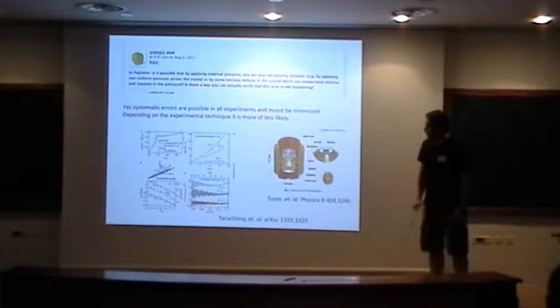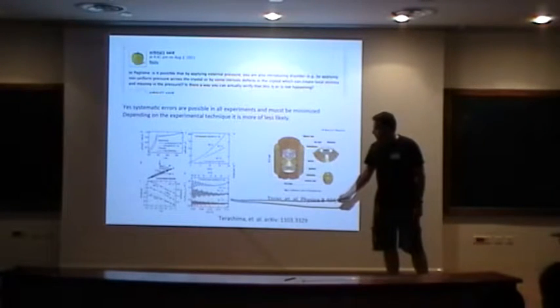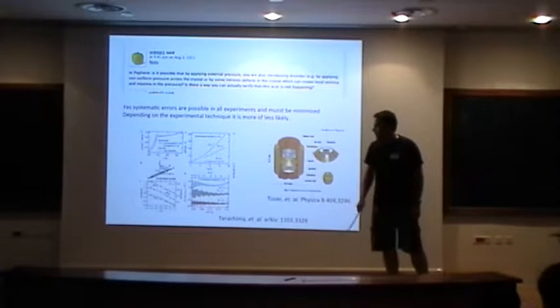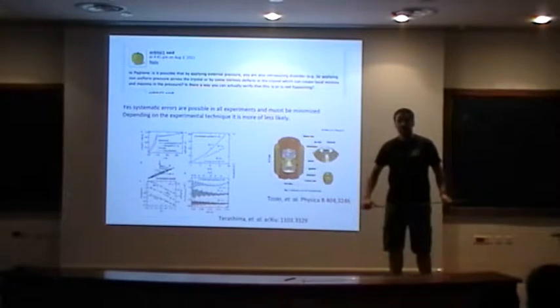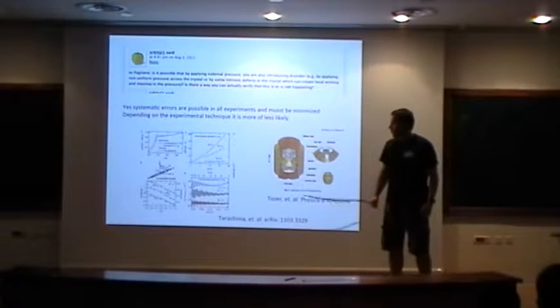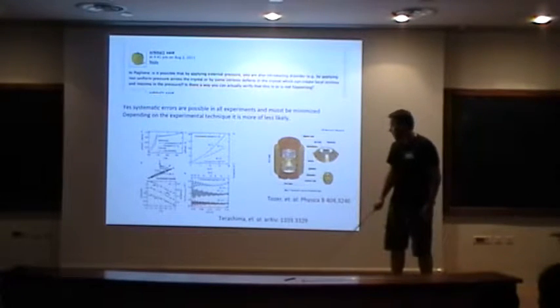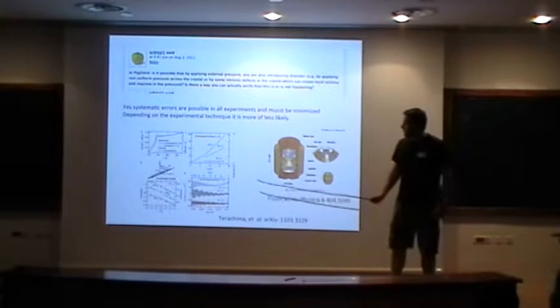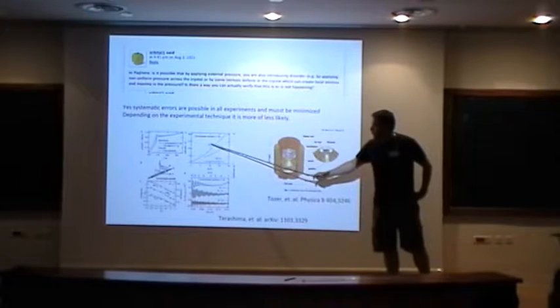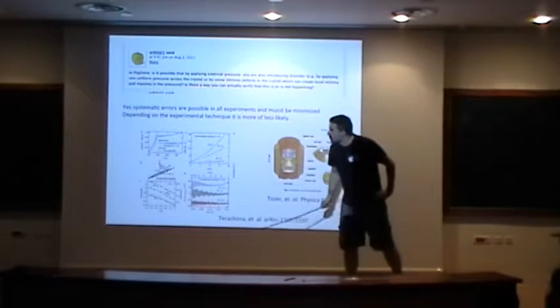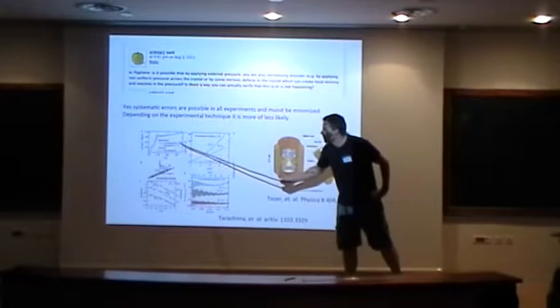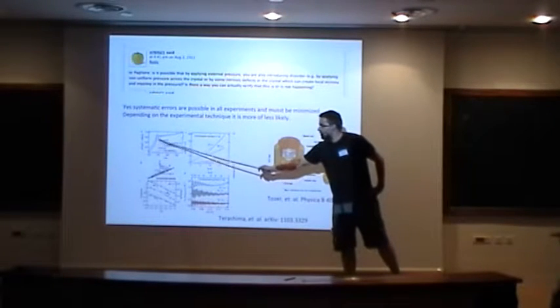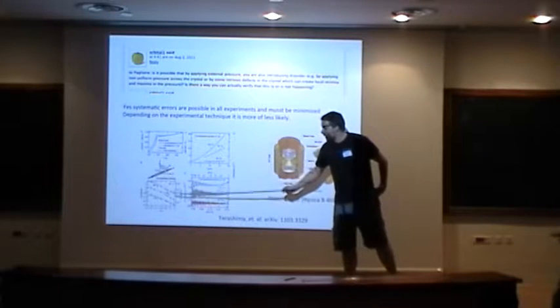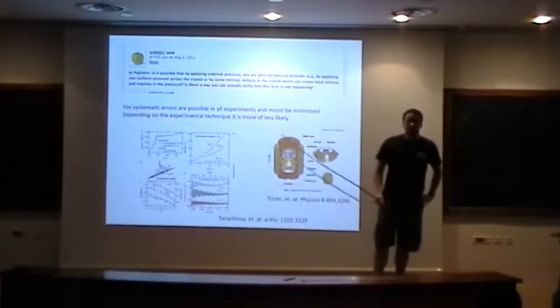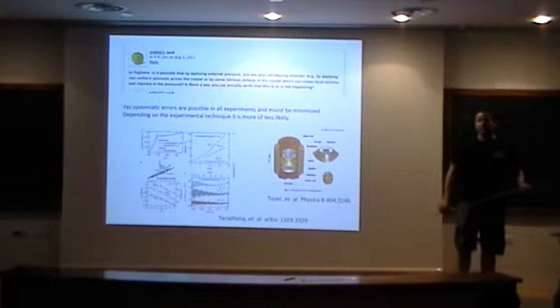Well, the best way that they verified so far was in barium iron arsenide. There was a great challenge to actually see quantum oscillations because of twinning. And what the group from Hiroshima did just recently, published on the arXiv, is they applied pressure along the b-axis, sorry. And you can see that there is a change in the resistivity. Due to that, they were able to see quantum oscillations, which is not possible if you would introduce defects into your sample significantly by pressure.